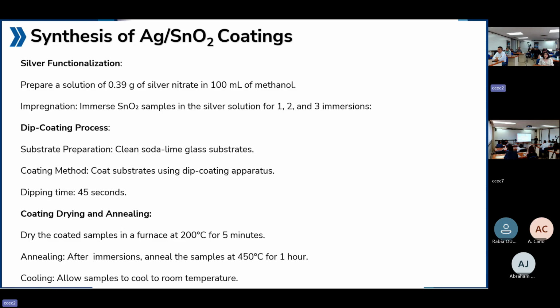Part 1 was referred to an article which is already published, and it was confirmed that the 3 immersed tin oxide coatings showed maximum sensitivity for this application. On the other hand, to do part 2, we added 0.39 grams of silver nitrate in 100 ml of methanol solution. This solution was used to dip the tin oxide coatings at 1, 2, and 3 layers, depending upon the immersion times, which are 1, 2, and 3.